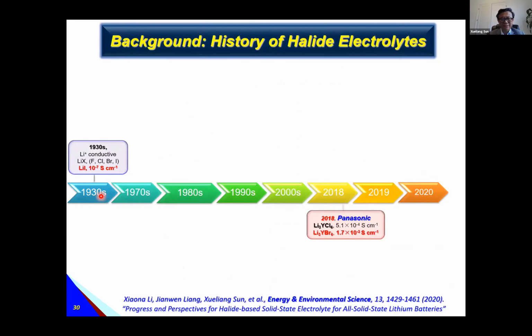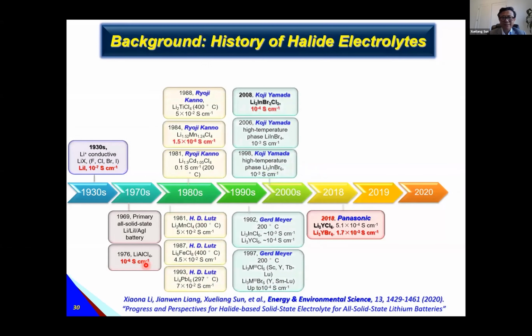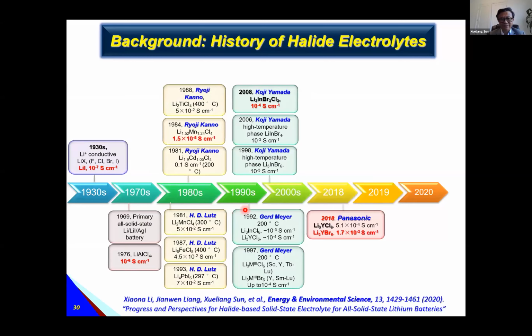Actually, in the earlier days, in the 1930s, the first reported ionic conductivity was 10⁻⁷, and then after 40 years, the second report got 10⁻⁶. And then after the 1990s, around 2000, 4 groups made great contributions. For example, Professor Kanno published many papers in the 1980s. They brought the ionic conductivity from 10⁻⁶ to 10⁻⁵, and then to 10⁻⁴. Then Panasonic brought it to 10⁻³.